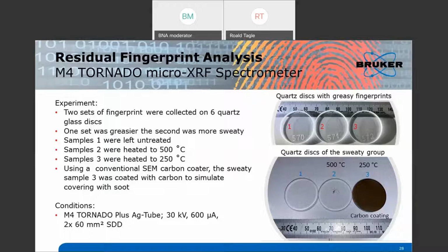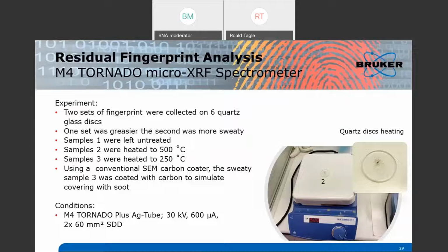We measured that several times, and we exposed them to different conditions. We exposed set number 2 to heating at a temperature of 500 degrees, and number 3 we heated up to 250 degrees. And this one we also coated with carbon, using the normal laboratory carbon coater as you use for SEM analysis. So basically this is the treatment that we did, and you see, for example, here our heating setting, and how the disk looked after several hours sitting on a plate at a temperature of 500 degrees. It was really carbonized, and it looked very different than expected.